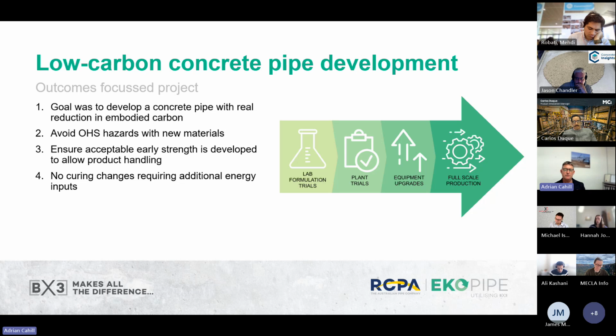We need to be able to move the pipes ideally within about 10 hours of casting. So that early strength is critical. And ideally, we wanted to avoid a requirement for significant curing. As you might have noticed on the video I showed, for standard concrete, we don't need to do any curing control. The pipes can stand in the ambient conditions.